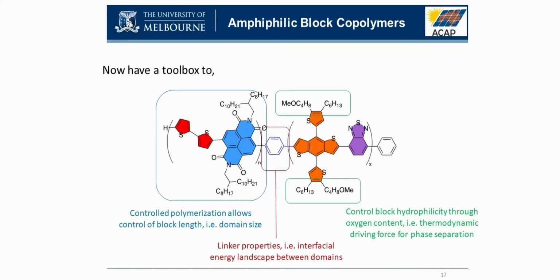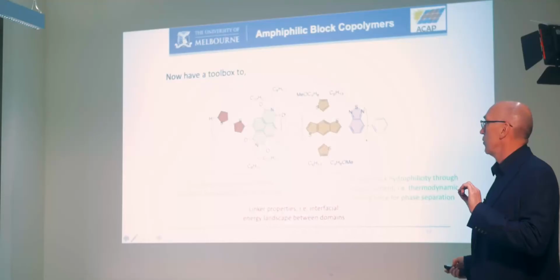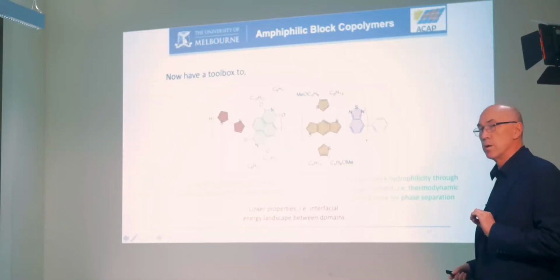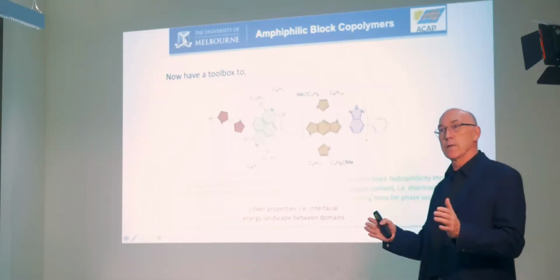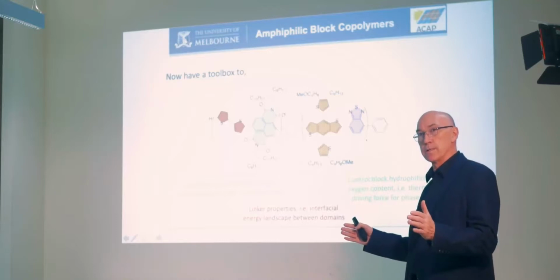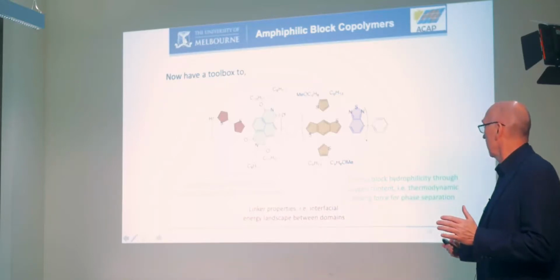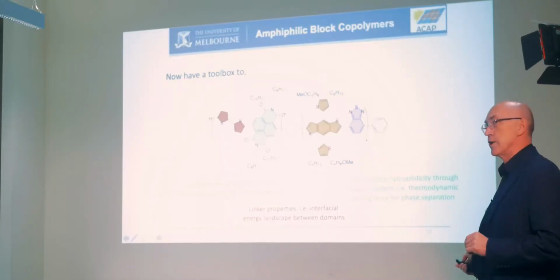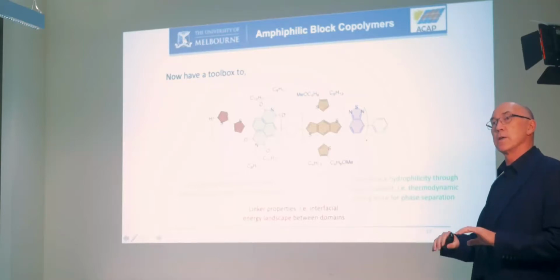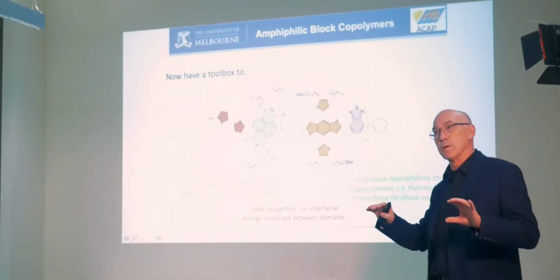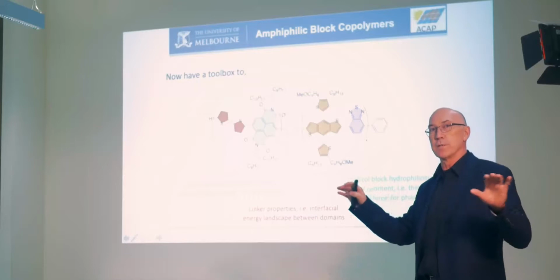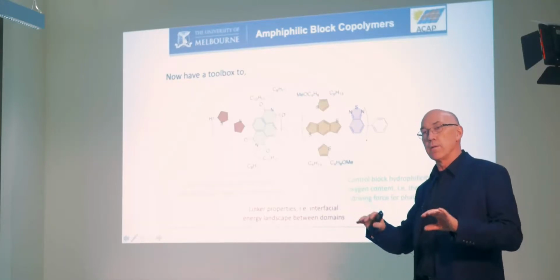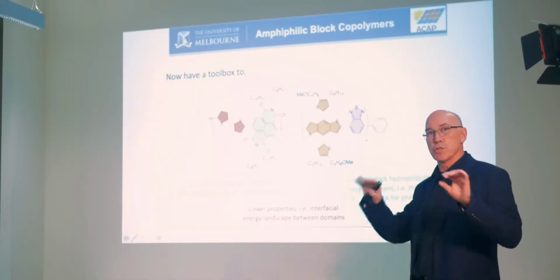So we have now a method of polymerizing an asymmetrically push-pull monomer, in a really controlled polymerization, to control the block length. If we control the block length, we can control the domain size. We can also change the amount of oxygenation on the side chains here. We can change the free energy difference between the blocks and therefore force phase separation. And therefore we should be able to push it so that we get really good phase separation.